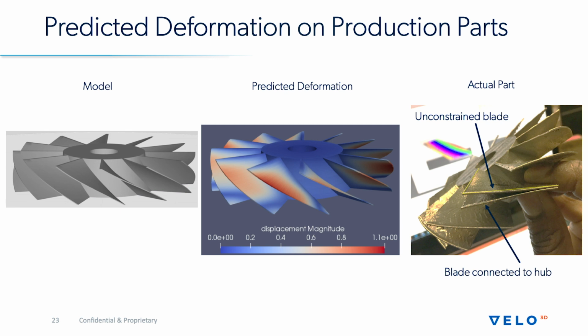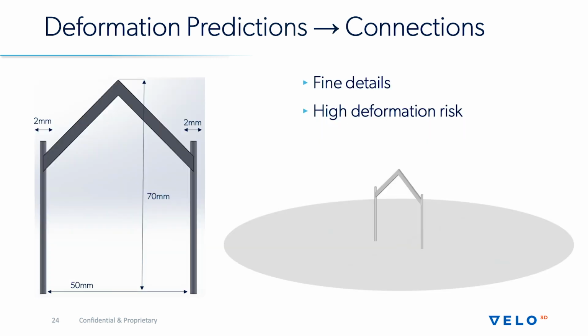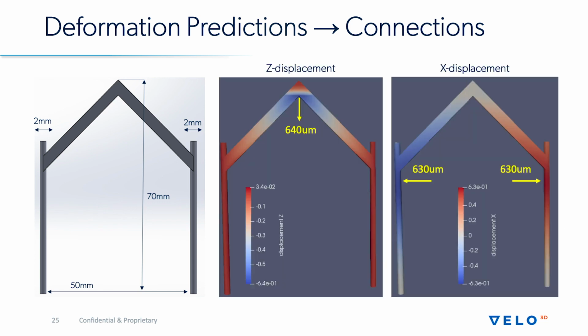Another very common example that we found on many parts of areas to watch out for large-scale deformation is connections. So this is a toy part, but it's very indicative of things that happen on real parts. In this case, it's a simple vertical wall structure, which then turns into a series of planes growing at 45 degrees, which then merge at some point within the Z height. So it's a very simple part. When you actually run the simulations on it, though, you end up with a very complicated answer, which is that the part is going to move a lot.